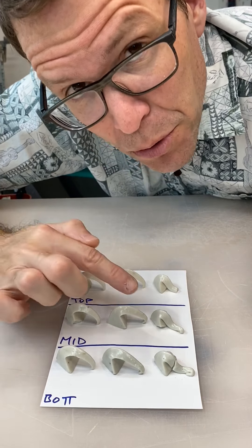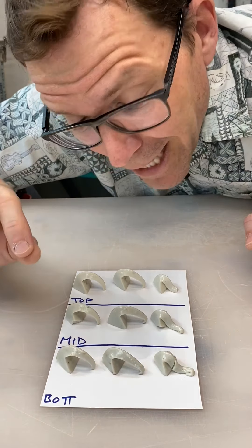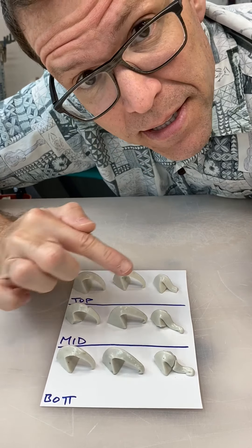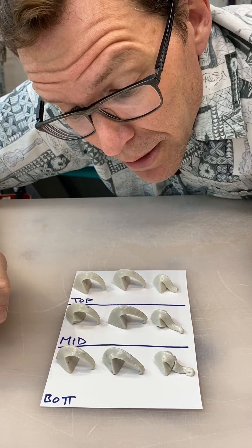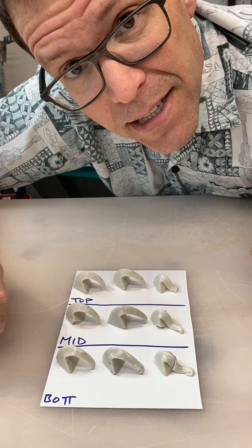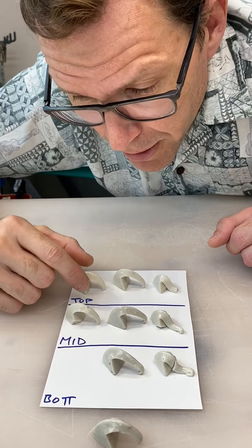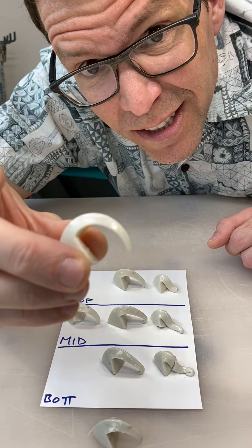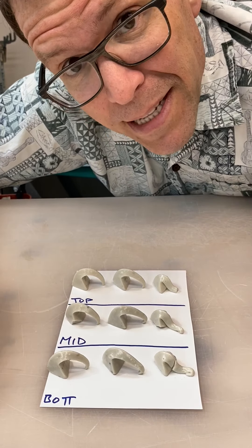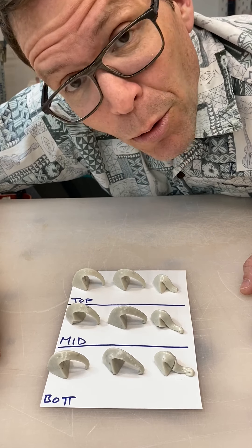Remember what we talked about — that's only about a 29-degree difference between these two cones. The good thing about the fancy digital control is I can actually go in and adjust the pyrometers to account for the fact that it's firing a little hot right now. So I'm going to reload the kiln with nine more cones, adjust the sensitivity, and see if we can get it perfect. We want this middle row to look like perfectly arched cones. I think you all get the idea of what it's like to replace the thermocouple and element in the kiln — so we're going to call this Tiki Technical Tuesday all done. I will see you next week!